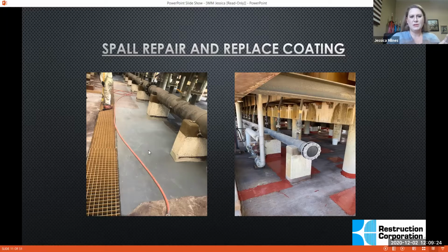A mention on this concrete: this is not the concrete that you see in a ready mix truck when you're cruising down the road. This concrete is very, very specific to this environment. The reason we use specific concretes in environments like this is, number one, the mine isn't going to shut down for us. They're not going to stop running so that we can go in there and wait 28 days for standard ready mix to cure before we coat it. So this specific concrete that is poured here is 98% sulfuric acid resistant.